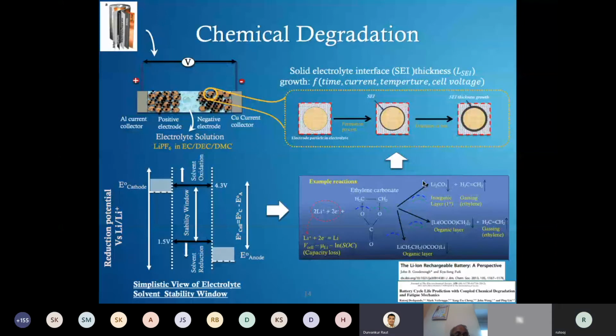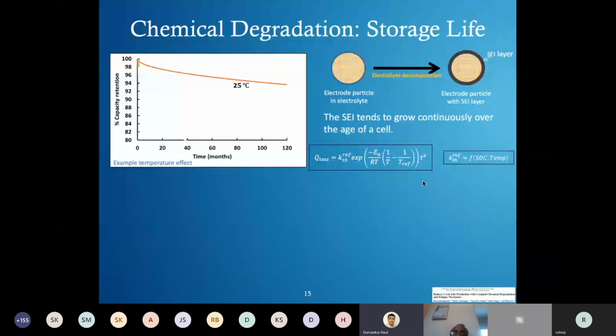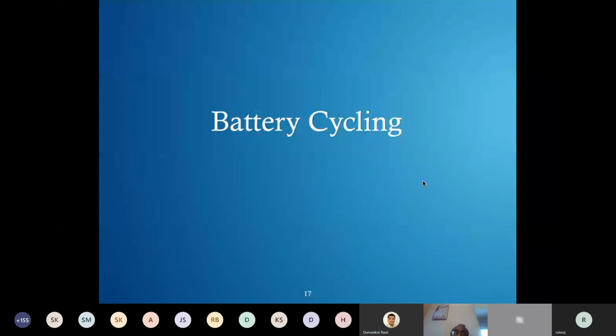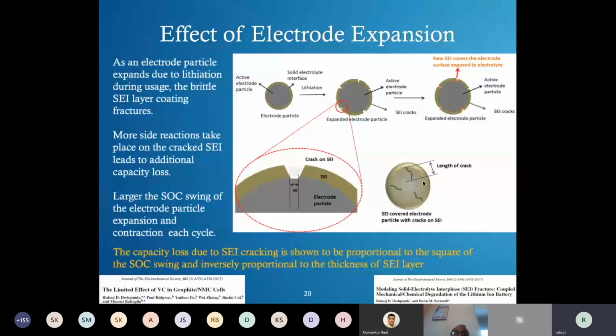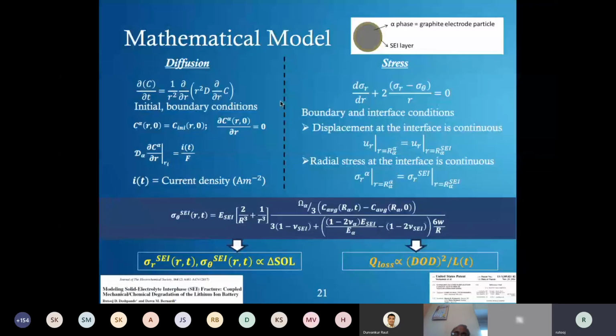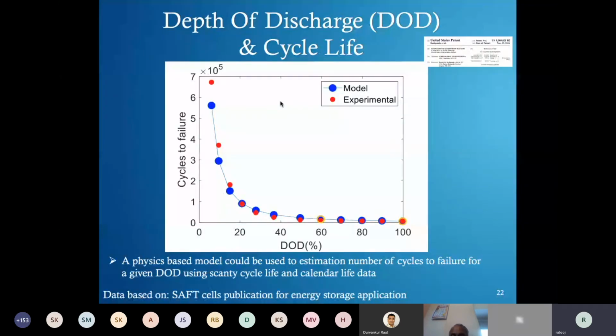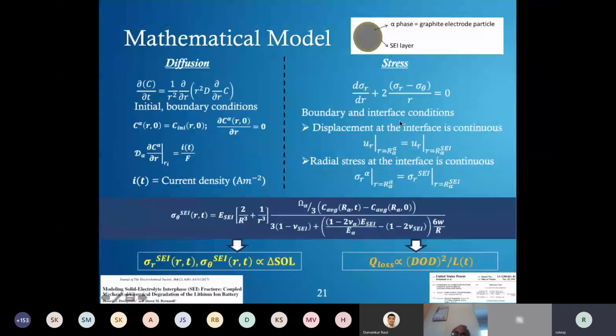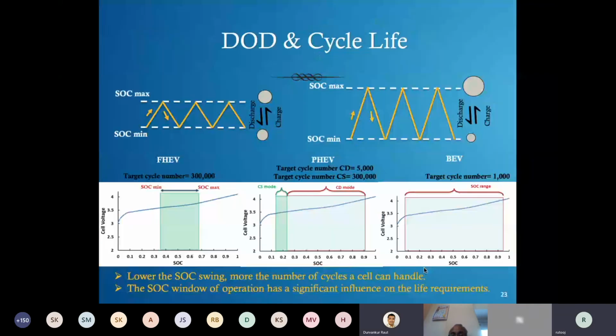Okay. Can you repeat the point regarding capacity loss versus DOD in short? Yeah, sure. So basically, depth of discharge will tell you how much your electrode is expanding and contracting each time you are charging and discharging. The larger the expansion and contraction, the more the capacity loss. In fact, for a given cycle, the capacity loss in that particular cycle is proportional to the square of depth of discharge. It's not true for all the cycles. I mean, it's not constantly proportional. This relation is changing, but in a given cycle the capacity loss would be proportional to the square of depth of discharge. So the higher the depth of discharge, the more the capacity loss. Does that answer the question? Yes, yes, it answers it.